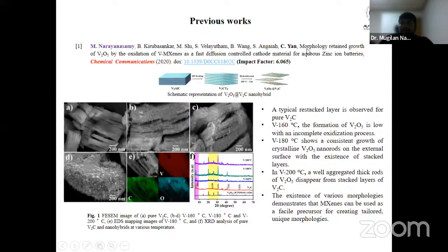This is the morphologically retained growth of V2O5 by oxidation of V-MXenes, acting as a cathode material for zinc ion battery. It was published in Chemical Communications in the year 2020. Here we can see that I used vanadium aluminum carbide, V2C, as a MXene, and I have directly used my V2C MXene in hydrothermal heat treatment.